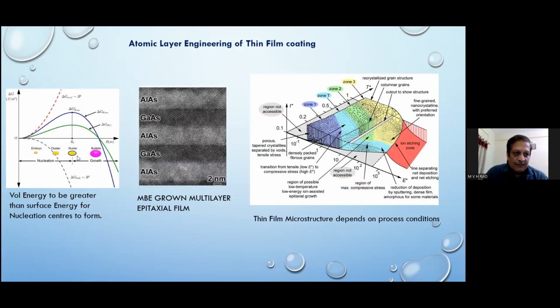So, atomic layer engineering. When atoms come together, there is always a first one or two atoms, three atoms, four atoms. As they come together, there is a combination of free energy, thermodynamics a little bit: the surface energy of the nucleus and the volume energy. Only when the volume energy is more than the surface energy will it become stable. Otherwise, there is a critical radius of this nucleus, and till that radius is formed, it will not be stable. Suppose 4-5 atoms come together and the surface energy is more, they will break up and become atoms again. But if the volume energy is sufficient, suppose 10 atoms come together in one shot, then the overall volume energy is better and it will be a stable material. So this is what the thermodynamics controls, the atomic arrangement.